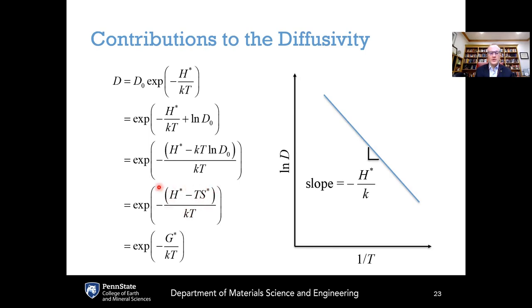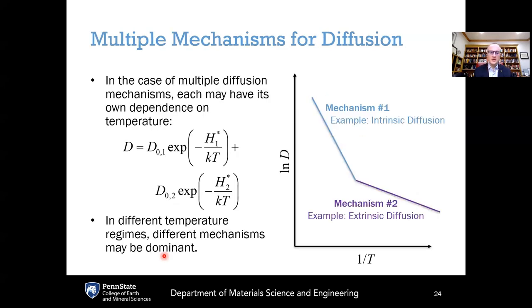This numerator should now look familiar to you. This is an enthalpy term minus temperature times an entropy term. In other words, that is a Gibbs free energy. So this entire numerator here is an activation Gibbs free energy, or an activation free energy, which we can write as G star. So another way to write this equation, building this prefactor into the argument of the exponential, is e to the minus activation free energy over kT. These are all equivalent ways of describing the same process. It's just that sometimes you can get more insight writing it one way versus another.